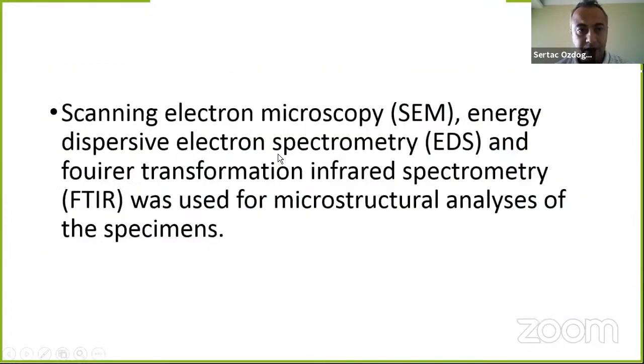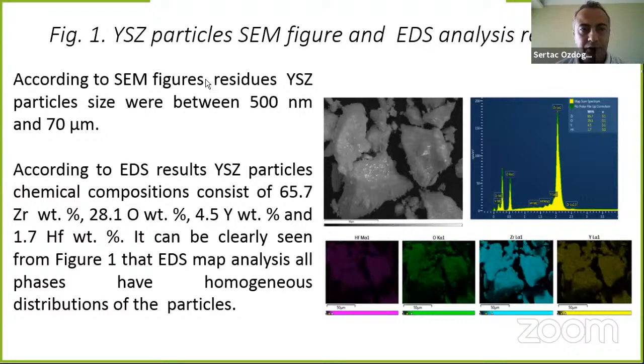In this study, we used scanning electron microscopy, energy dispersive spectrometry, and Fourier transform infrared spectrometry for microstructural analysis of the specimens. In figure 1, we can see the YSZ particles, SEM figure, and EDS analysis results. According to SEM figures, residue YSZ particle sizes were between 500 nanometers and 70 micrometers.